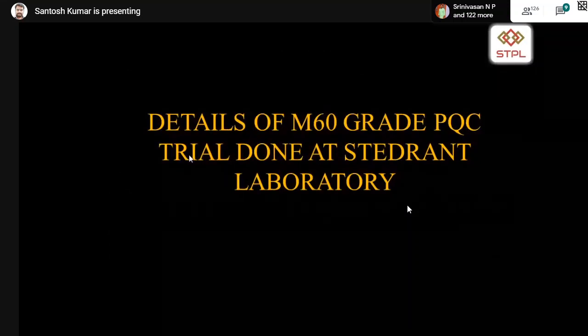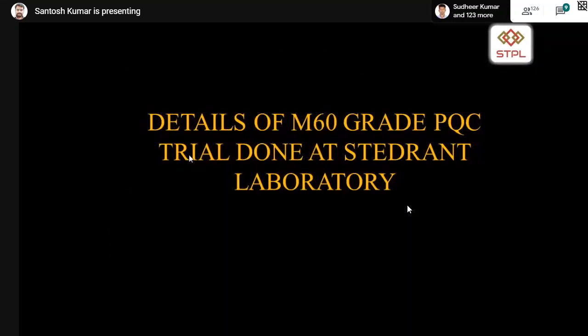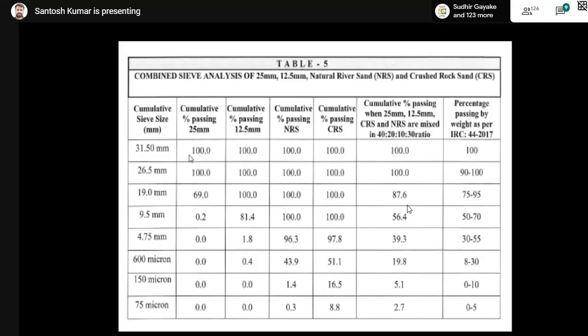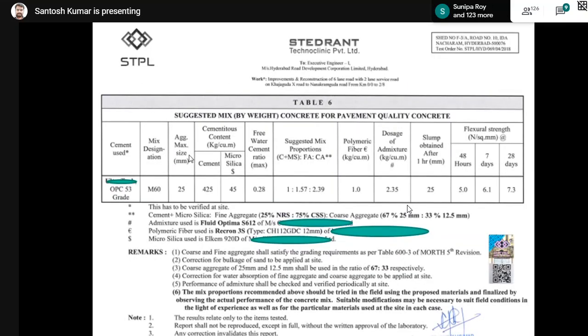So details of M60 grade pavement quality concrete, trial done in Stedrant laboratory. This is a mix design which we have done practically for a site, I can say. You can see here in this mix design we have used 25 mm, 12 mm, river sand and crushed sand in different proportions. And you can see the mix design. Cement content was taken as 425 kg. Microsilica taken was 45 kg.